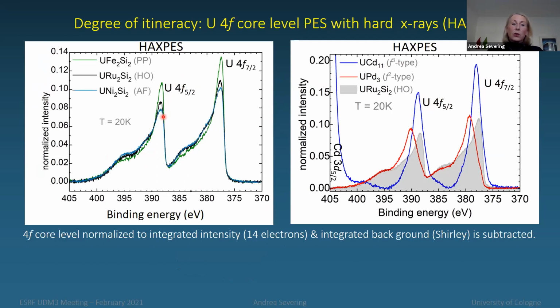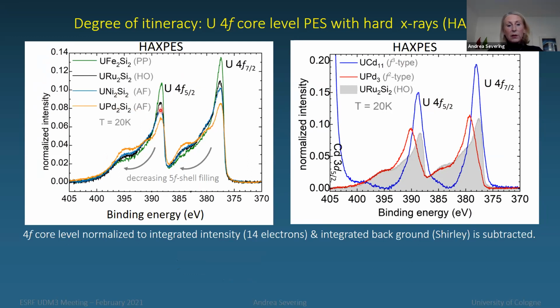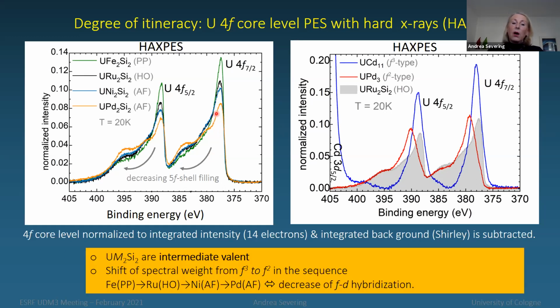And now let me come to the antiferromagnetic compounds, the nickel and the palladium. And we have a successive decrease here, but increase there. So what we are seeing is a successive decrease of intensity from more F3 to more F2 in the sequence from the Pauli paramagnet via the hidden order to the two antiferromagnets. All compounds, of course, are intermediate valence because they all share the features of both the palladium 3 and the cadmium 11. We also can say, because we know they all have the same ground state symmetries, any changes in the spectrum can only be due to changes in the configuration, not due to different fingerprints of the ground state symmetry.